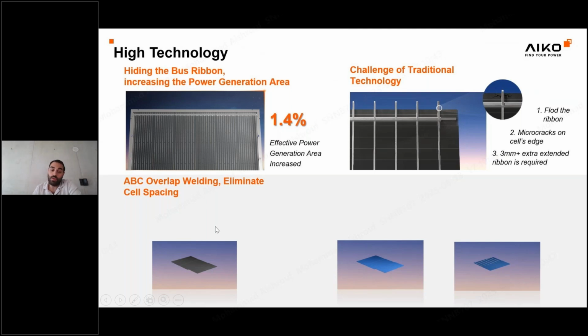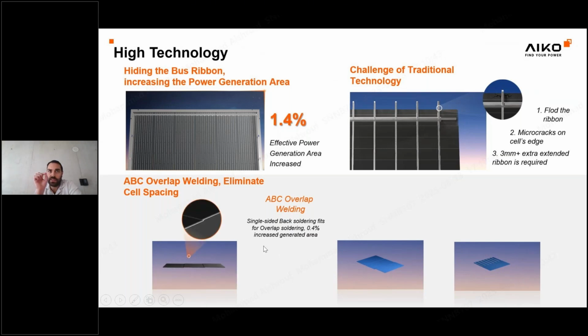The other improvement we have done in order to reduce the non-cell area was to overlap the cells, as you can see here. As you know, the cells have small horizontal gaps, and what we have done is overlap these cells, and this also improved the effective generation area by 0.4 percentage.